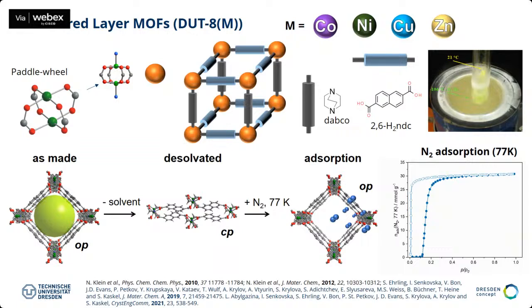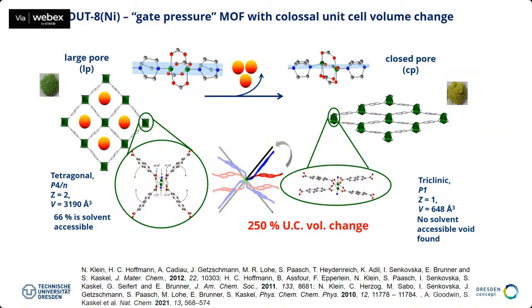And this shows basically the flexibility of this type of material. Here you see also a little bit what this means for the structure in detail. So in the large pore structure, we have a very regular tetragonal binuclear complex, the ideal paddle wheel structure. But in the contracted phase, the driving force for the contraction is basically the van der Waals forces between the naphthalene rings. This is the driving force.